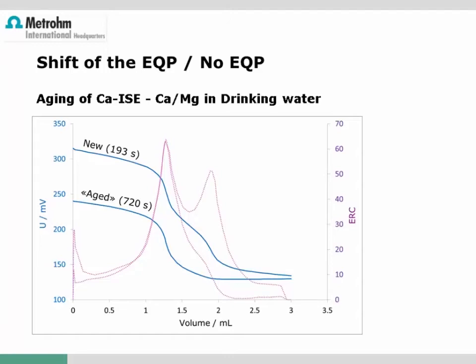However, this changes with time. Again, the first indication, we're not looking at further titration details, is that the titration duration takes longer. The titration curve then shows all the details. The overall response of the sensor has decreased, the potential jumps have become much smaller, and the second equivalence point to indicate the magnesium, which is very sharp for the new electrode, has almost disappeared. This may result in either a missing equivalence point for the magnesium, or the reproducibility of it getting poor.